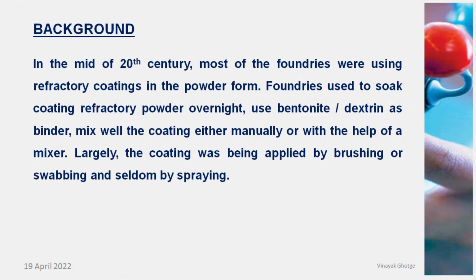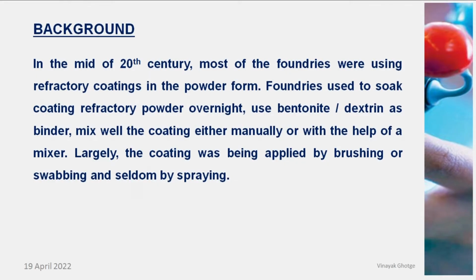See, in the mid of 20th century, most of the iron foundries were using refractory coatings in the powder form only. The foundries used to get refractory powders like zirconium, graphite, and they used to use either dextrine or bentonite as a binder, soak the powder in the binder overnight, and then use a mixer or even a small mixer so that they can use this coating. And mostly these coatings were being used by either brushing or by swabbing, and seldom by spraying also.